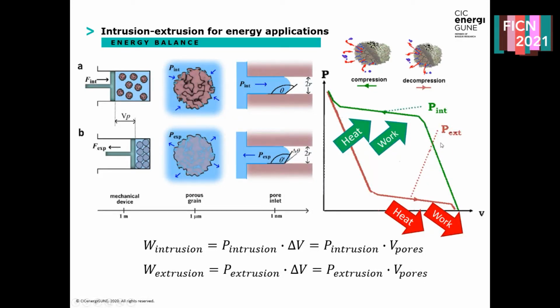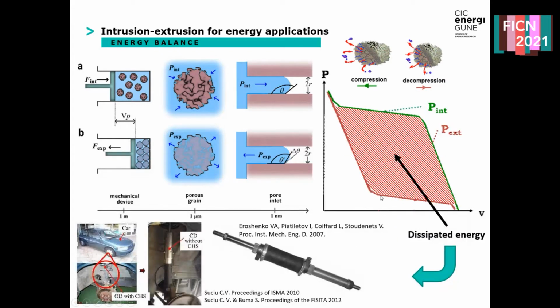Now, the process of intrusion-extrusion is typically hysteretic. So upon decompression, the extrusion pressure, so the pressure at which pores expel the water and become dry, is much lower than the intrusion pressure. And during this extrusion process, the system releases the mechanical work which was accumulated during intrusion, and also it releases heat during the exothermic extrusion. Now, this hysteresis can be very, very pronounced in terms of energy,